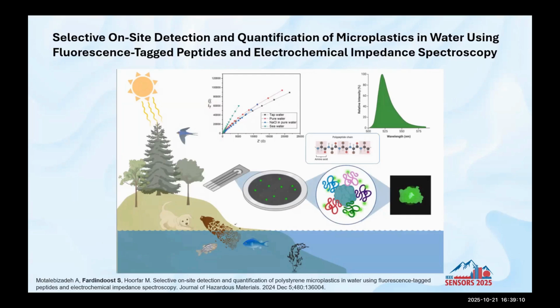So fluorescence was good as a first validation of the developed technique, but was not enough for our purpose. We moved to electrochemical measurements, and that was good. We just coated the screen-printed electrode with peptide and used different sources of water. It was good as long as your water is clean, meaning drinking water or very pure water. But when it comes to seawater, because of the high ionic environment, and the whole basis of electrochemistry is electron charge, the high conductivity of the seawater doesn't help for measuring electrochemically. It was not successful for real world samples.